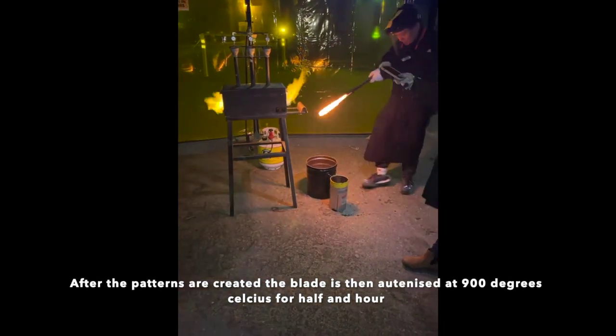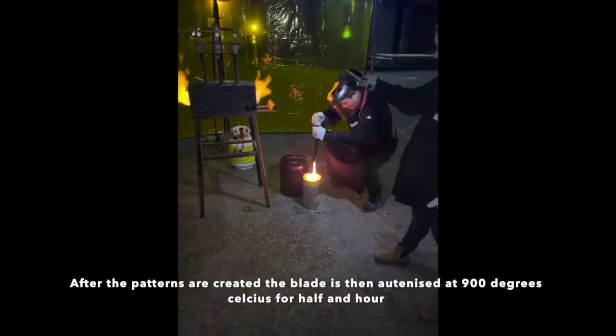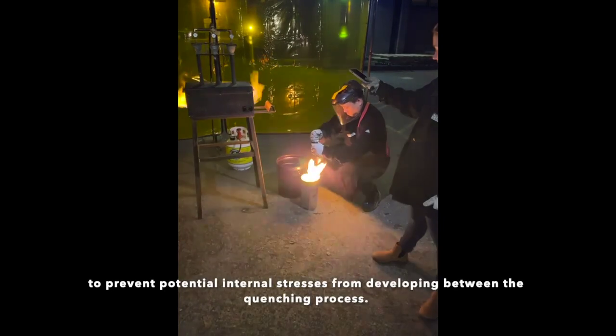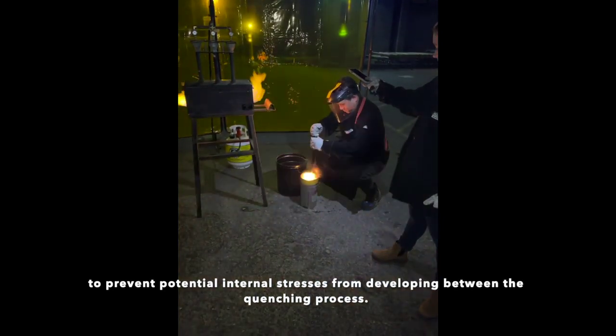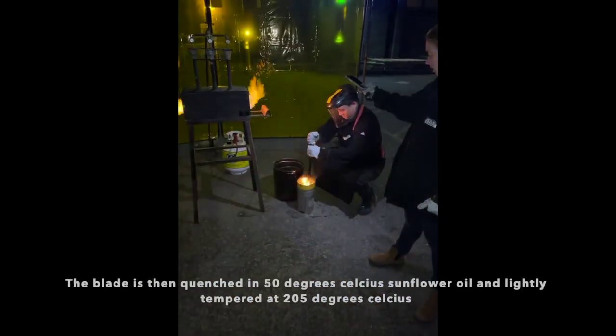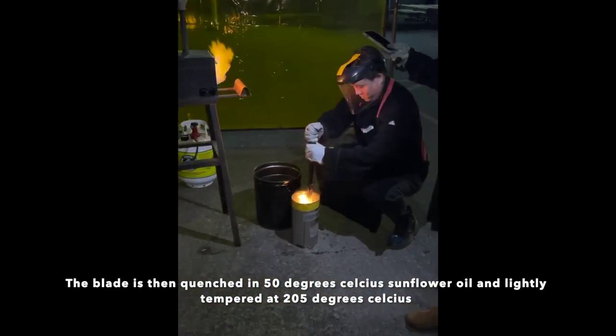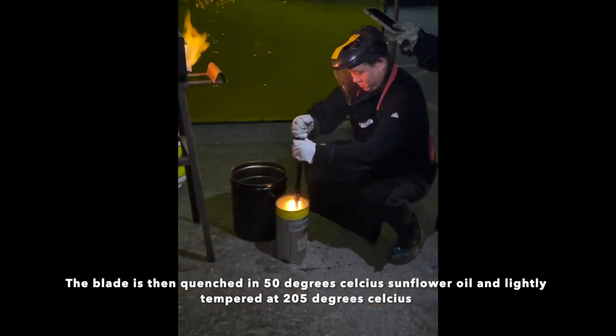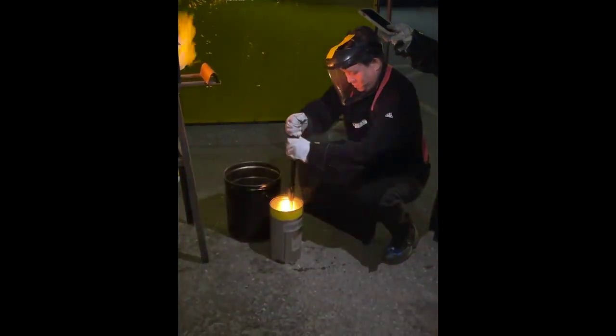After the patterns are created, the blade is then austenized at 900 degrees Celsius for around half an hour to prevent potential internal stresses from developing during the quenching process. The blade is then quenched in 50 degrees Celsius sunflower oil and lightly tempered at 205 degrees Celsius.